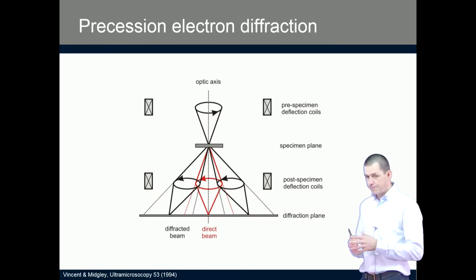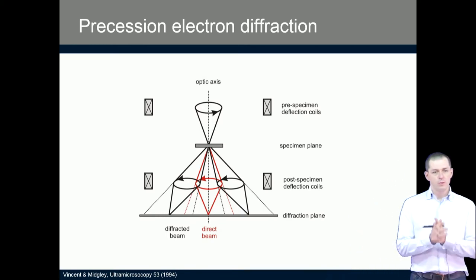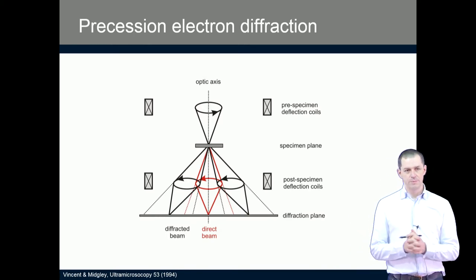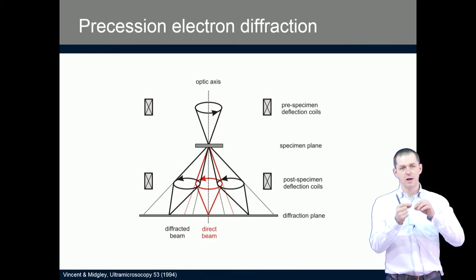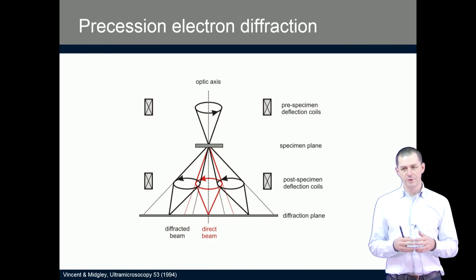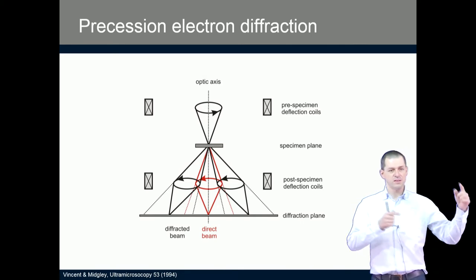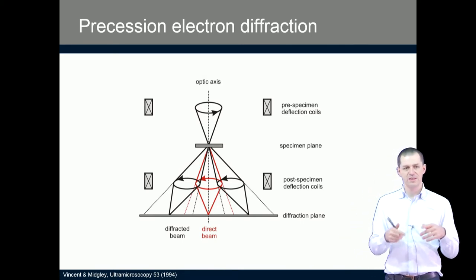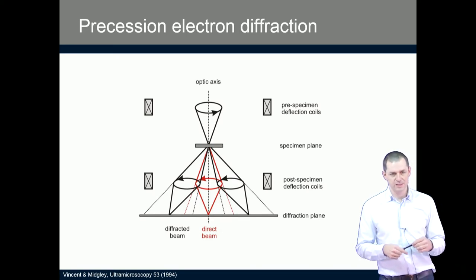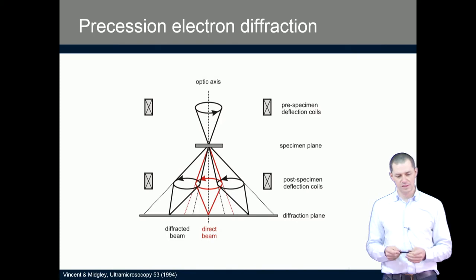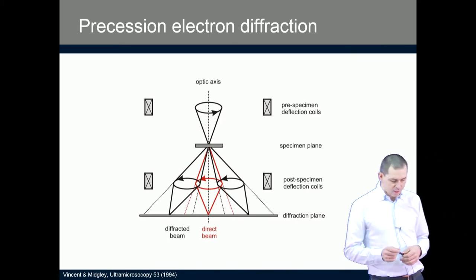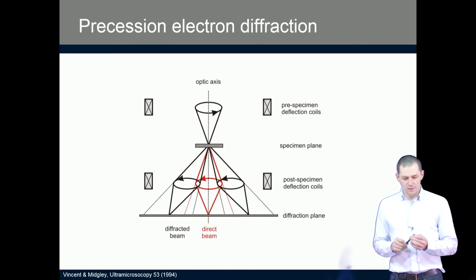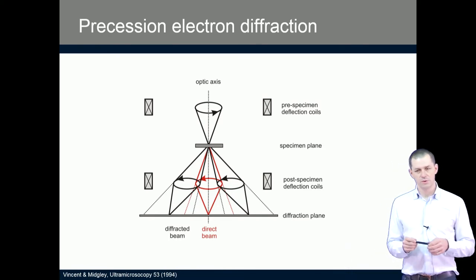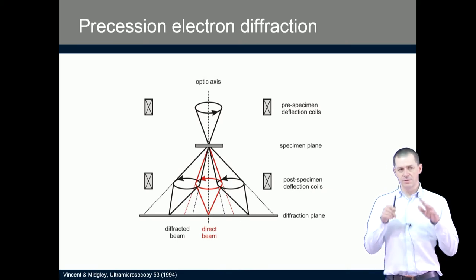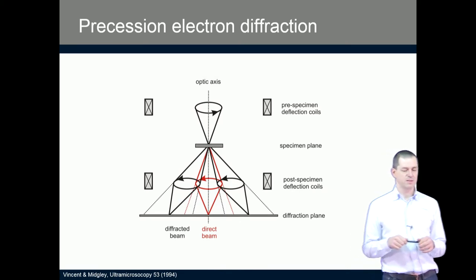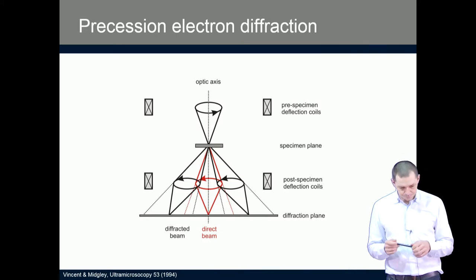However, these patterns are most affected by dynamical diffraction, because in oriented diffraction patterns there is a large number of simultaneously diffracting spots, and the intensities of the spots mutually influence each other, and the resulting intensity is therefore strongly affected by dynamical effects. In 1994, a method of precession electron diffraction was introduced, which aimed at suppressing these strong dynamical effects in oriented diffraction patterns.